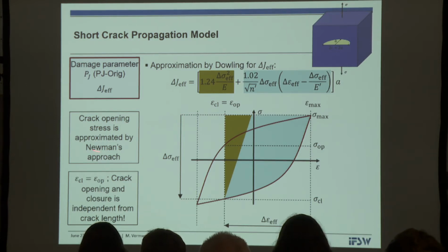And I should mention that the crack opening stress here is taken from Newman's approach, from Newman's well-known equation. And just to repeat, we identify opening and closing along a vertical line. So we have only one history variable in our simulation, and this is the current location of the crack opening strain.